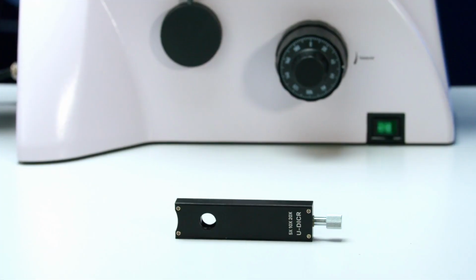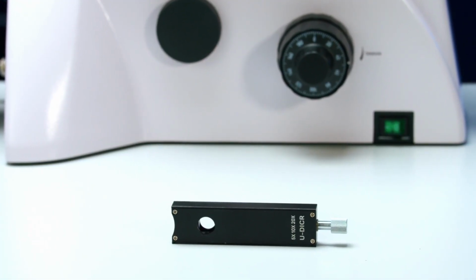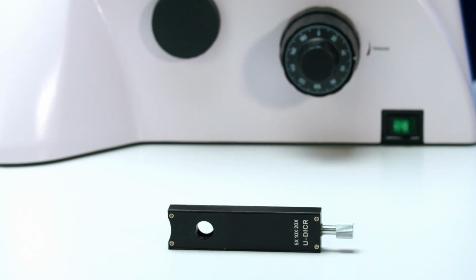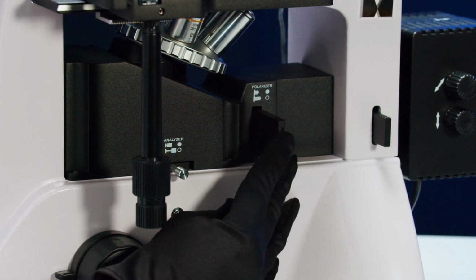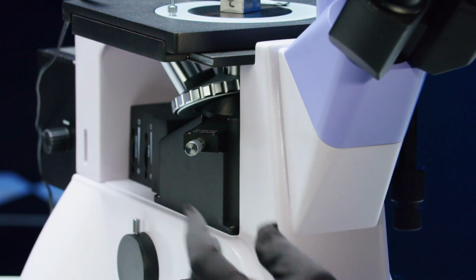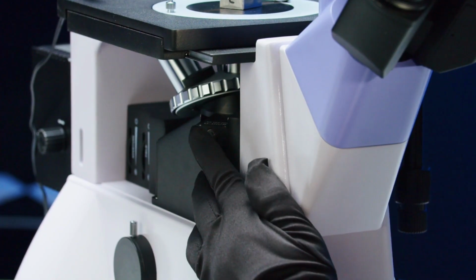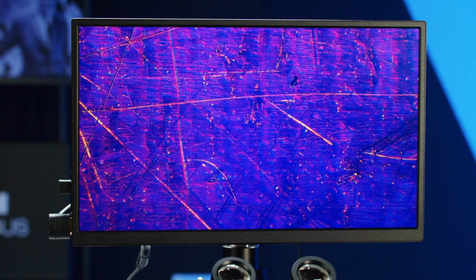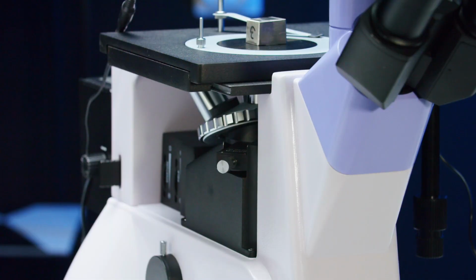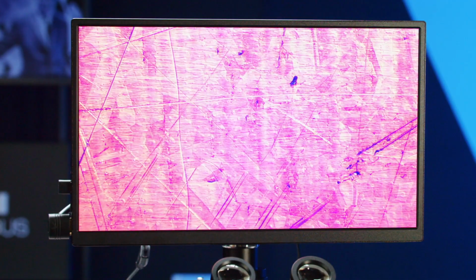The MAGUS Metal V700 DIC model implements the DIC method for objectives with magnifications of 5 times, 10 times, and 20 times. A special module is included in the kit for observation using this method. The polarizer is set in a crossed position relative to the analyzer. As a result, the field of view becomes dark. Next, the DIC prism is introduced into the optical path. Then, the aperture diaphragm and light brightness are adjusted. By rotating the prism knob, we adjust for an even distribution of colors across the field of view. As a result, we obtain a clear relief image.